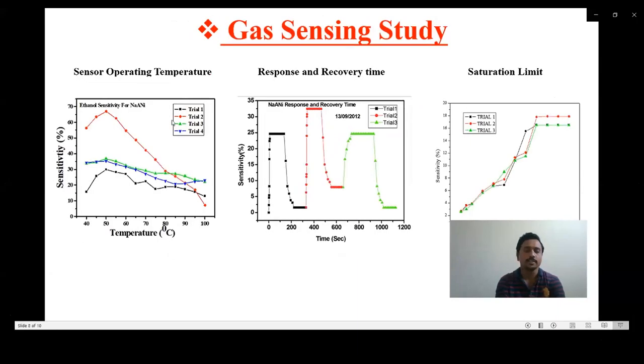This is the sensing study, the main study of the experiment. The sensor can operate at a low operating temperature, only 50 degrees Celsius. This graph shows the response and recovery time, which are very quick, which is very good for the characteristics. And this is the saturation at 800 ppm.